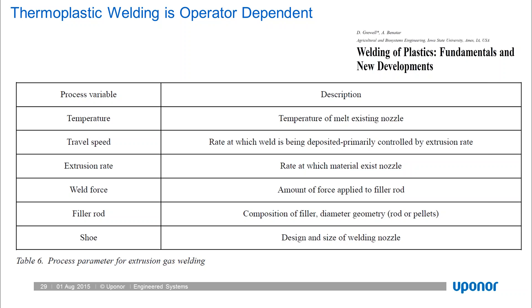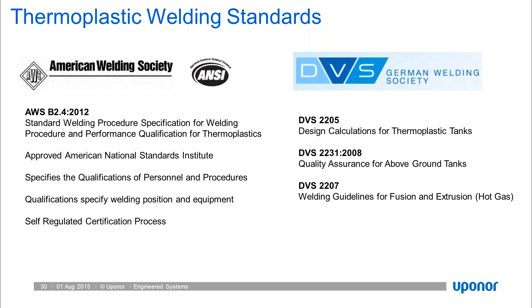The temperature or melt of the nozzle, the rate at which the weld is applied, the rate at which material exits the nozzle, the amount of force applied to the filler rod, the composition of the filler, diameter of the rod or pellets, and the design of the welding nozzle all come into play, as well as preparation of the material to be welded. For this reason, extensive standards have been established. In North America, we have the American Welding Society, specifically AWS B2.4:2012, Standard Welding Procedure Specification for Welding of Thermoplastics—a self-regulated process whereby the manufacturer develops a quality control program meeting AWS B2.4:2012.